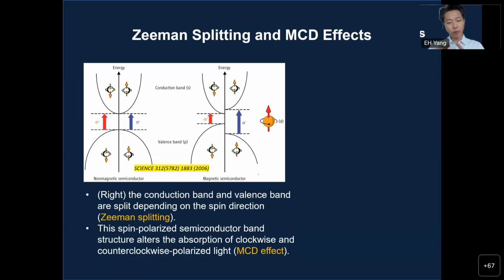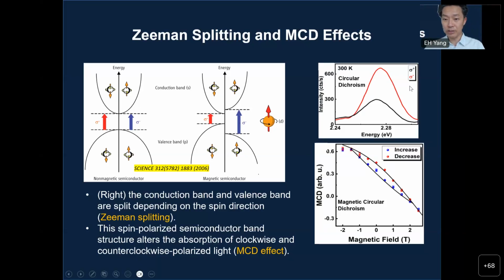And this spin polarized semiconductor band structure, therefore, also alters the absorption of clockwise or counterclockwise polarized light. So that's called the MCD effect. That's exactly what we see here. On the top right, it's the intensity versus energy. So there is a circular dichroism, basically. Okay, so it's absorption, and you shine this light with left-handed and right-handed polarization, and then the absorption is different. So that's exactly what you see, and you see that at 300K.